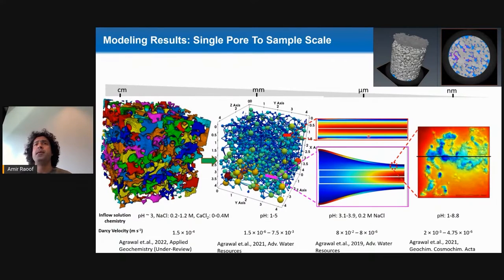This is a pore, which is much larger. So this part is a small piece of this pore. And then you have one pore, and we did experiment and numerical analysis on the single pore to see how this pore from initially would change, would open up because of the dissolution. And then from the information of this rock, we plugged it into the pore network modeling to see how the dissolution changed fluid flow of the sample. Also, because we did X-ray tomography, we have the pore structure of the rock as shown here, to see how the pores are growing when reactions have taken place.